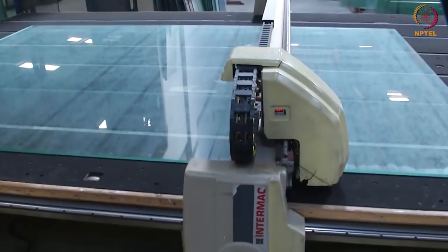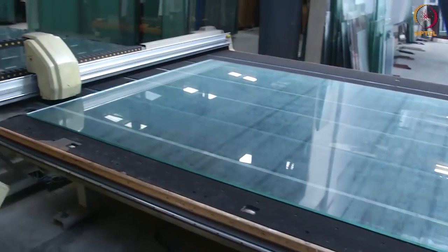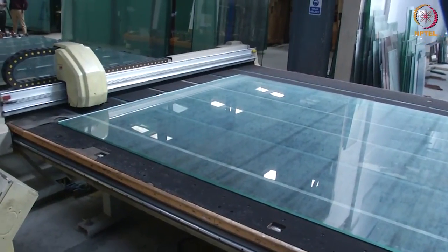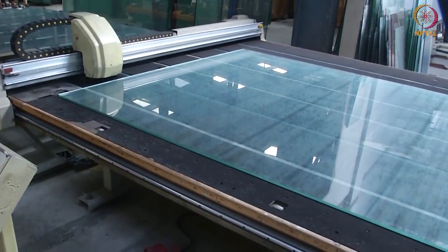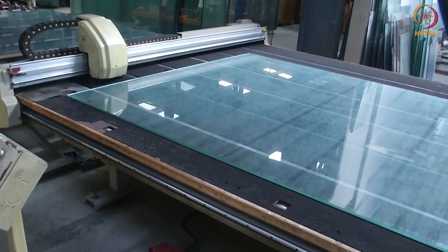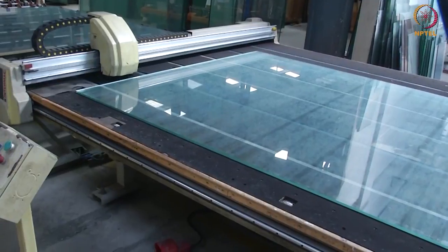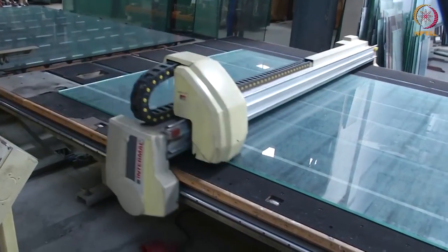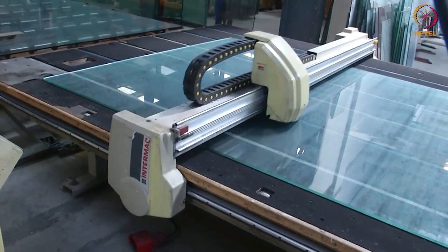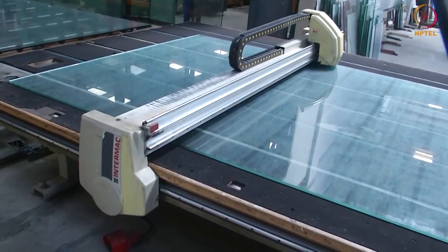So with the help of cutting oil, it will give impression to the glass. It will have cutting wheels inside that head. Based on the glass thickness, different cutting wheels can be used. For 12 mm thickness, we use 155 degree angle cutting wheel. Now it is making a marking on the glass.